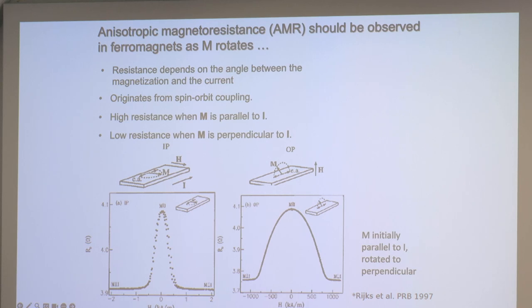One of the things we wanted to look at was anisotropic magnetoresistance, which is looking at what happens to the resistance as you rotate the magnetic field in plane or out of plane. In this case, AMR generally occurs when you have magnetization parallel to your current. From scattering, you get high resistance, and when magnetization is perpendicular to your current, you get low resistance. So you expect a peak like this that varies from high resistance to low resistance, depending on the orientation of your magnetism with respect to the current.